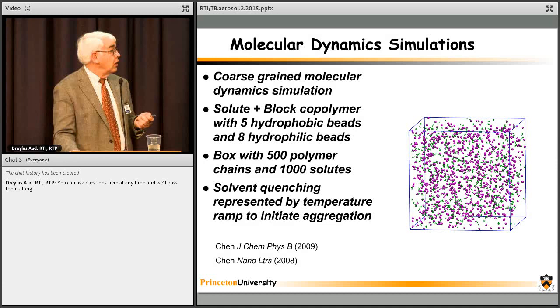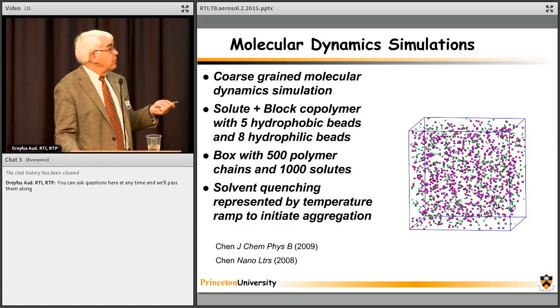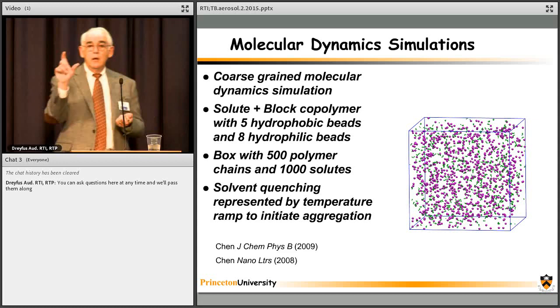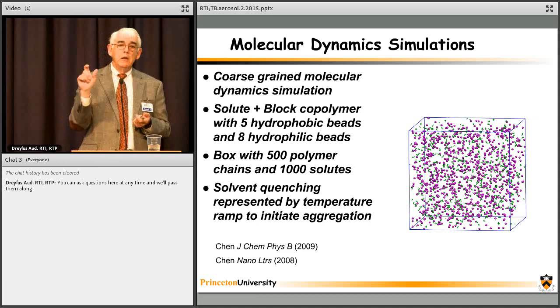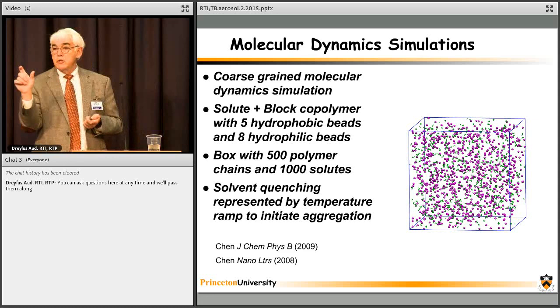So working with a simulator in our department, Thanos Panatopoulos, and a postdoc, they did this molecular dynamic simulation, and this box shows a box which has the block copolymer and a hydrophobic drug molecule, where they have matched the PEG molecular dynamics interaction potentials with PEG to give the right radius of gyration of that chain. And the hydrophobic blocks of that polymer, we're changing that interaction potential with the hydrophobic solute, which is precipitating. So it's a coarse-grained molecular dynamics.